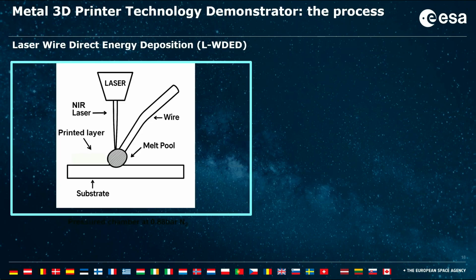Now, if we look a little bit more closely at the process we selected, we decided not to work with powder, for the reason we have talked about before. So we selected a wire-based process. With wire, you don't have a problem with reduced gravity. And we selected the direct energy deposition process.